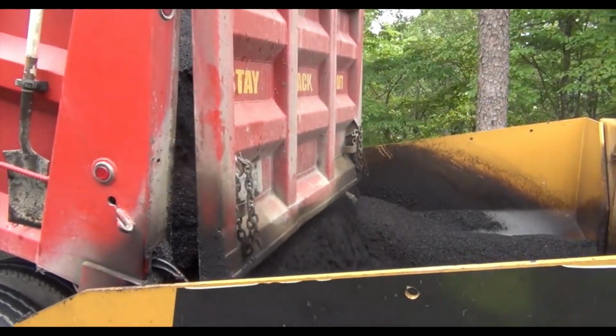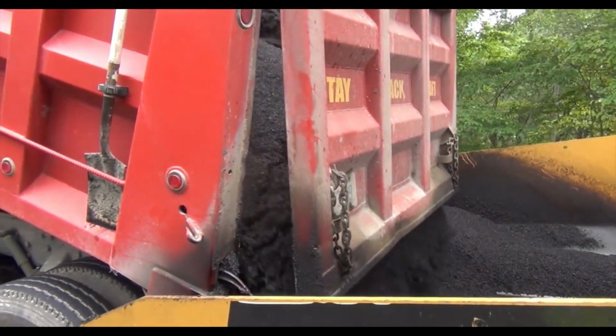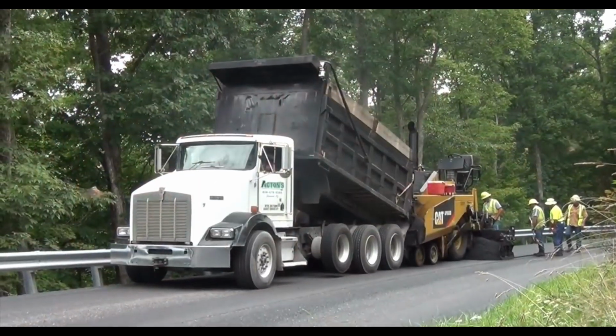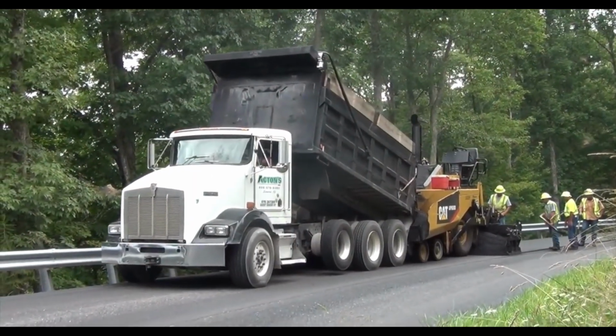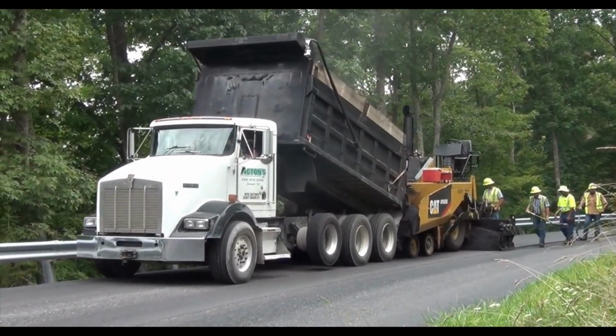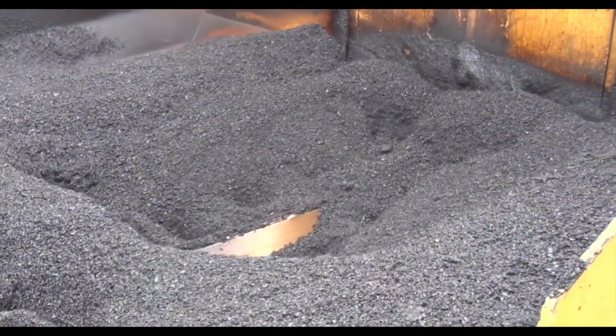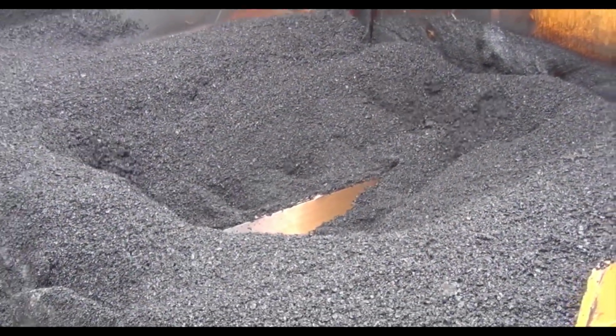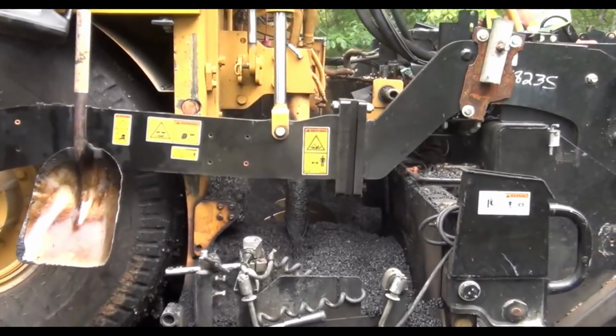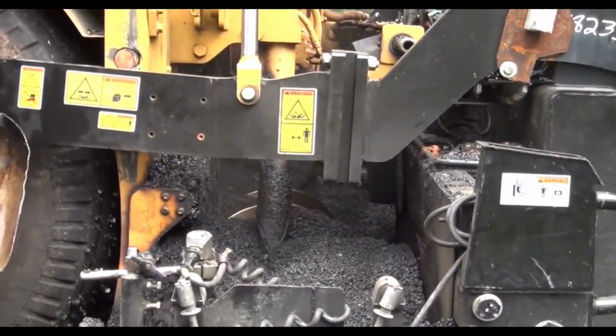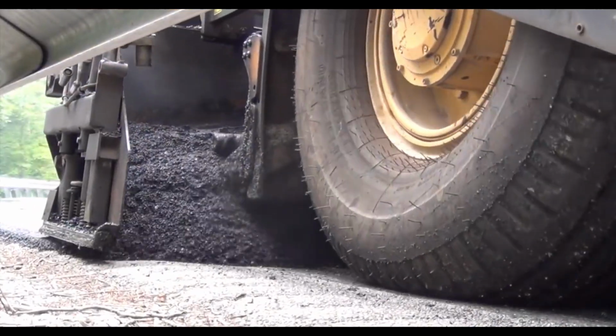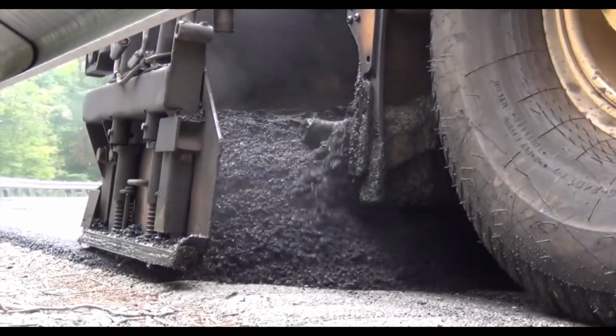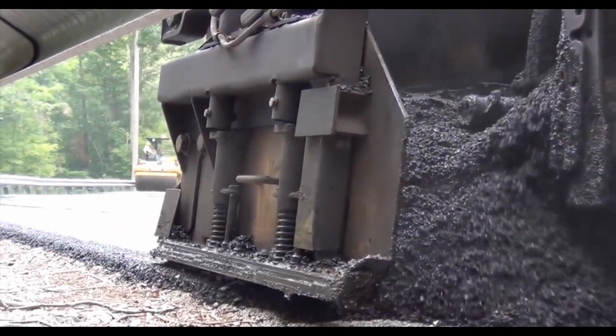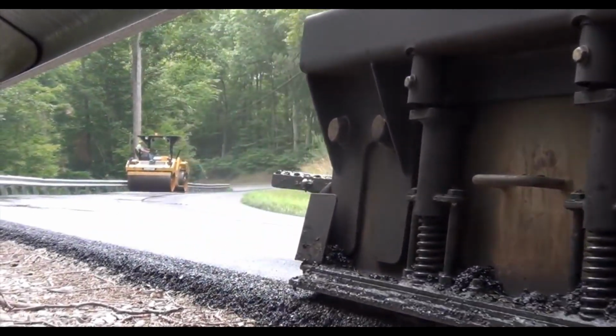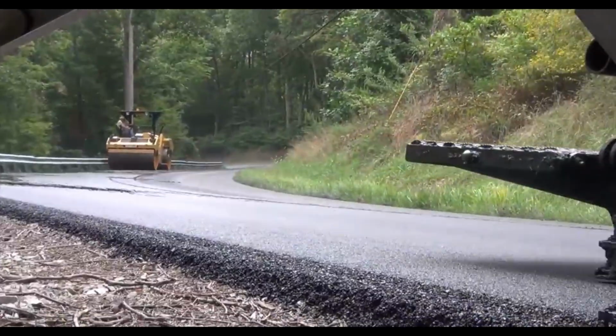The MTV or dump truck unloads the mix directly into the paver. This is the machine that actually lays the finished asphalt surface onto the roadway. A conveyor and augers are used to evenly distribute the asphalt mix before it exits the paver at the rear. The asphalt is applied to the roadway by the screed, which is a plate that can be adjusted up or down in order to produce the specified consistent pavement thickness.